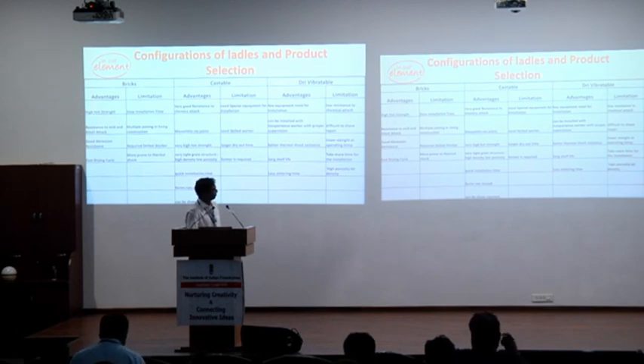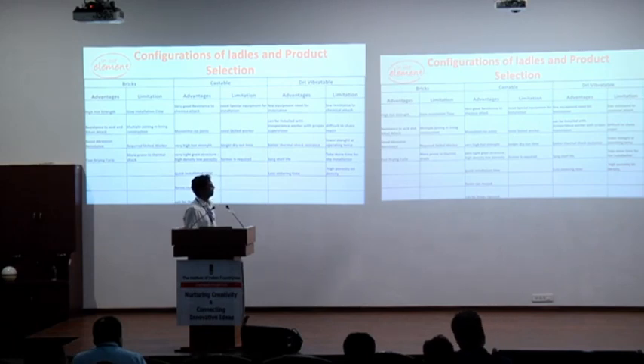When it comes to dry vibratable, few equipments are required, easy to install, better thermal shock resistance, and shelf life is more compared to castables, because castables have some cement which does not have that much shelf life, maximum it's like 6 months. And it has a less sintering time compared to castable.